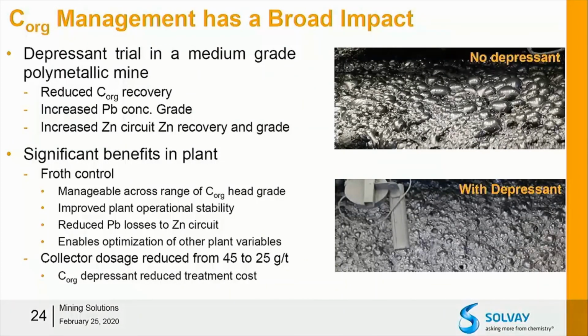Carbon creates a very sticky, unstable froth, and it was forcing this plant to operate at significantly reduced airflows. There were significant operational stability issues, particularly with variation in the carbon head grade. And with the introduction of the depressant, now they could operate consistently and manage variation in carbon head grade. They could increase airflows and decrease their froth depths to maximize lead recovery in the lead circuit, so you had fewer lead losses to the zinc. And with that operational stability, now the plant's able to start optimizing other variables to actually maximize the overall circuit performance.